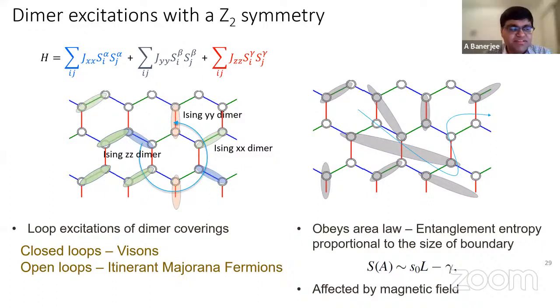Yes. So there is a paper that we published in PRB. The first author is Anjana Samarakoon, and I am the second author, where we looked at the results from quantum Monte Carlo versus classical Monte Carlo. And what we figured out is that some of the spectrum looks very different for the classical spin liquid. You can also get a classical spin liquid where basically the higher order Heisenberg terms are all neglected. So you are only doing a simple Landau-Lifshitz equation that you are solving in a semi-classical form. And when you do that,